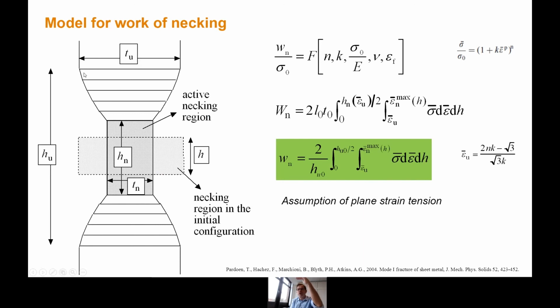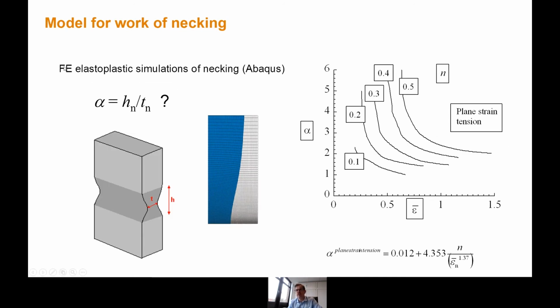You need to know the expansion of the neck in the length direction, or in the elevation direction. So the neck is not necessarily a one-to-one shape, but it may be longer. And indeed, if you run finite element simulation and you look at the profile of the length of the neck, you find that the height of the neck and the thickness of the neck are not giving you a value of 1, which you would get for a perfect plasticity material, but you're getting a value that is larger than 1, and which will be larger and larger as you increase the strain hardening exponent. The larger your strain hardening exponent, the wider your neck. It redistributes plastic strain, or it tends to delocalize the necking.